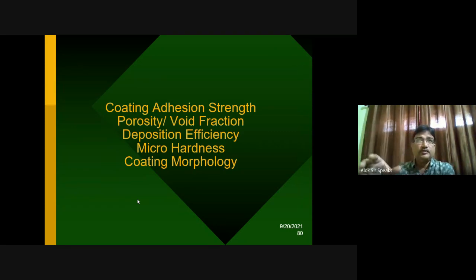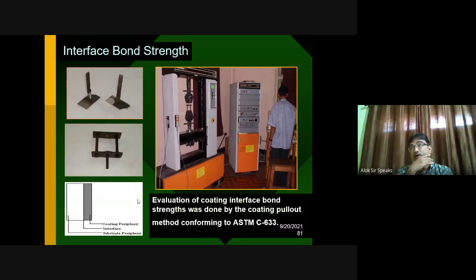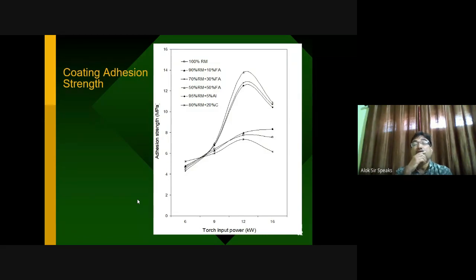After these coatings were formed, the characterization was done. The essential characterizations carried out were coating adhesion strength, measurement of porosity and void fraction, deposition efficiency, micro hardness, and of course the coating morphology was also observed under a scanning electron microscope. This is the setup, a very familiar machine, the universal testing machine, UTM. Using this UTM and a holder designed by us, we evaluated the adhesion interface bond strength, or the adhesion strength, following the ASTM standard C-633, and this is the variation of coating adhesion strength.